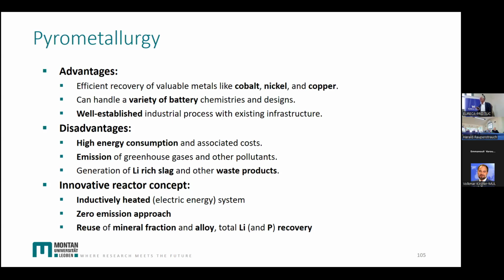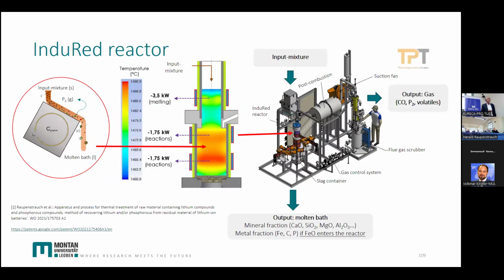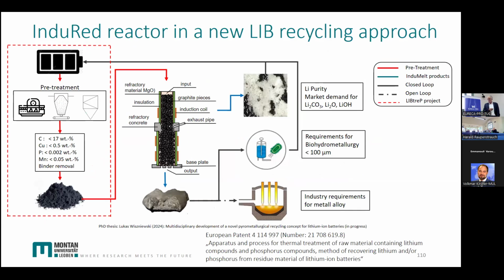Although I don't like this word too much, zero emission. And we can reuse the mineral fraction, the alloy, and we get the lithium and phosphorus as well, which you find in the black mass. So, similar approach as I mentioned earlier. We're running experiments on that. Here you see, for example, a picture out of our experiments. You see the lithium, which was formed very clean in the gas phase. The alloy, as it is, can go back to the industry. What I should mention, we have a European patent since a couple of months, and Canada and the United States are pending for this process. So hopefully we get the patent in a couple of months.